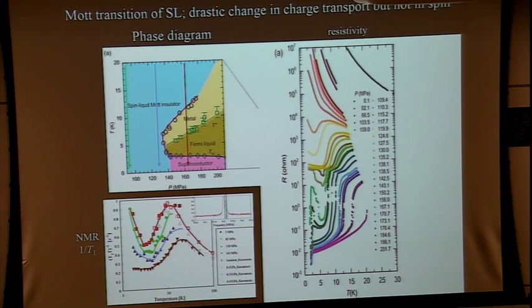However, in spin degrees of freedom, there is no qualitative difference. For example, if you look at the data above 3 kelvins, there is no qualitative difference. The gradual change. This is a Fermi, oh sorry, this is the Korringa relation. Here, in the metallic state, it's the Korringa relation, and the Korringa level is gradually lifted at lower pressures. Okay, so in particular, in this temperature range, this change is very smooth.